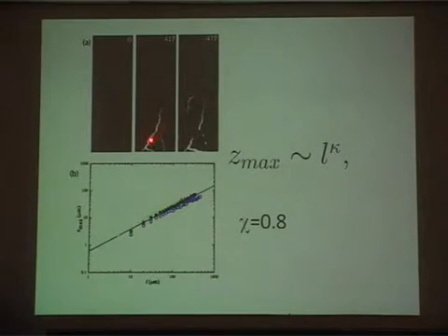And this is to show that every time you have a crack, so this is like zero field, and then you initiate the field, you have a Y-shaped crack here, then you have again a Y-shaped crack here. You can see that the crack is initiating somewhere here, which actually grows at a larger field to this. So essentially you have Y-shaped cracks, the cracks open, then you have an electric field which wants to, so if I have a flake like this, it is unstable equilibrium. This is the stable equilibrium because it's an anisotropic object, and the polarization will be such that the torque will be minimized if I just go up in this direction, and that's why the whole thing flips. So otherwise you'd see that once it has cracked, there is no reason for it to flip.